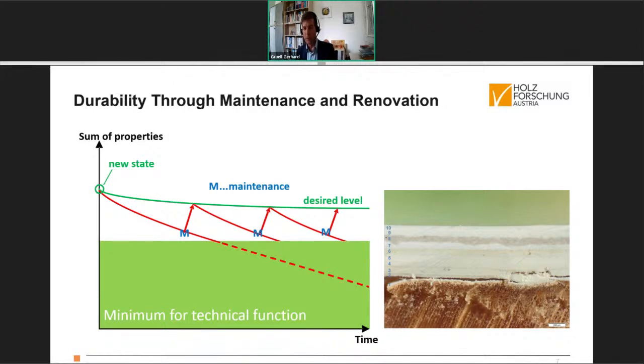The question is, how often can you do maintenance? I think this is not possible until infinity. You cannot lay up some 20 maintenance coats on top of this surface here because of two reasons. The first one is that the total dry film thickness gets too high. It may be already too high for this sample here. If this is 200 microns, it's about, say, some 600, 800 microns in total here. That's a lot. So the total dry film thickness is one factor.